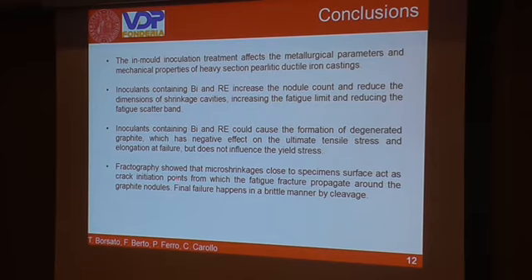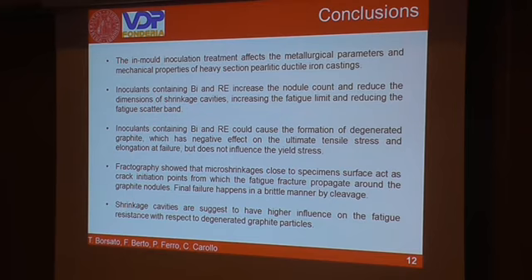The fractography showed that the microshrinkages close to the specimen surfaces act as crack initiation points from which the fatigue fracture propagates around the graphite nodules, while the final failure happens in a brittle manner by cleavage. In conclusion, shrinkage cavities are suggested to have higher influence on the fatigue resistance with respect to the degenerated graphite particles, in this case of heavy section perlitic ductile iron castings.